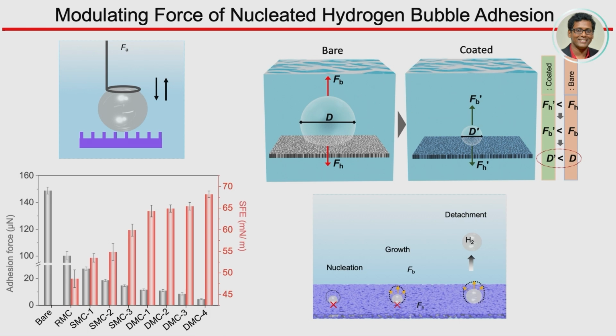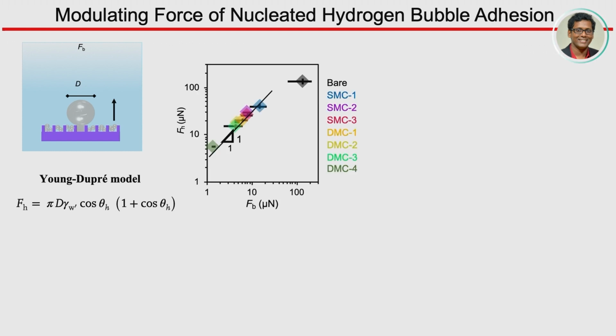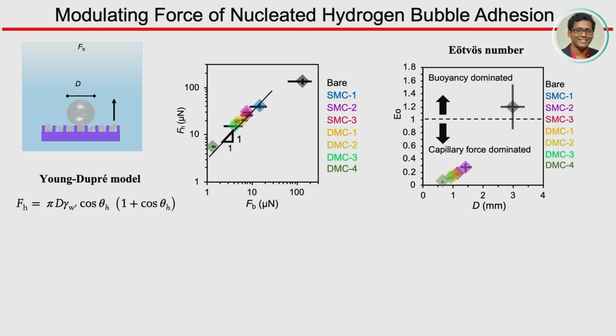Whether you can pre-detach or detach the hydrogen bubbles much earlier than this buoyancy-dominated regime, right? As we have studied, experimentally validated with this static bubble contact angle, we wanted to see what happened for the nucleated bubbles. For that we did this simulation using the Young-Dupré equations, and the simulation data is also showing a similar kind of trend. The Eötvös number tells that this phenomenon does not depend on the buoyancy force, rather it is a capillary force, okay?